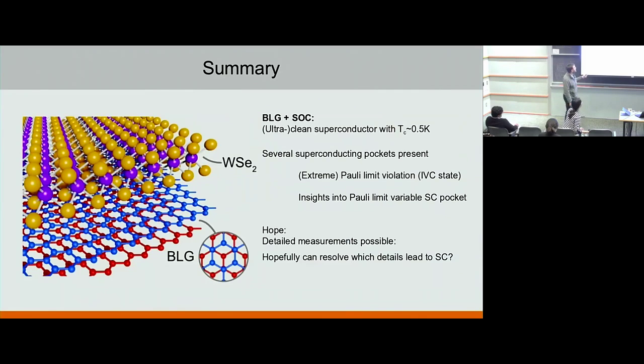Essentially, the beauty of this system is that it is an ultra clean superconductor with a manageable TC, where you can actually work and get decently high quality data. We found these strange superconducting pockets where, in one case, you have some Pauli limit violation, which is probably related to the IVC state. And in these other pockets where things are more complicated, you can provide some insights if you are willing to put time, effort and students into very careful measurements.